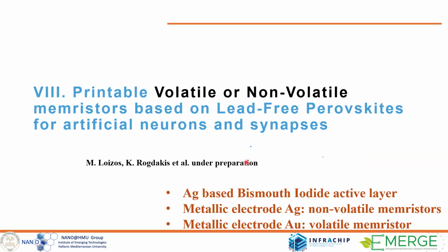Then we wanted also to achieve a non-volatile lead-free based memory, so that's why we changed again the stoichiometry. We put some silver inside our system. Then we found that when a silver pad is used, we can have a non-volatile memristive operation, while when we have gold as a pad, we have volatile memristive. So with the same structure, in terms of perovskite and the other layers, only by changing the electrode, we can tune between non-volatile and volatile memristive.